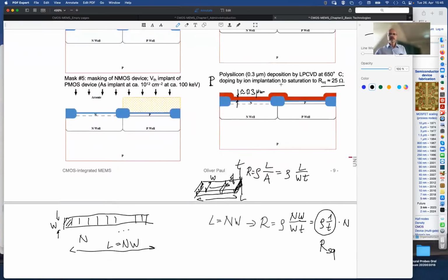And implantation to saturation means that not more phosphorus goes in. That means about 10 to the 21 per cubic centimeter of phosphorus doped into that polysilicon. So about 1% of the atoms are substituted by phosphorus. It's very high. If you put in more, then the polysilicon will react with the phosphorus, and then you'll have another material, but you want silicon. So don't put more in.